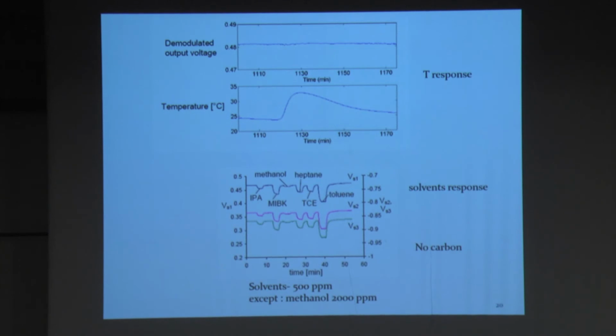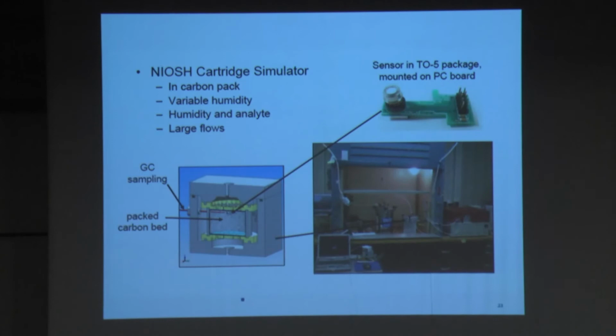Okay, here's the demonstration of the temperature dependence of the system. We increase the temperature, but the signal remains flat. And on the bottom part, you can see some signals after exposure to different solvents. Okay, so all three bridges act very nicely. So what we did next, we packaged it in a TO5 with a filter, inserted it in a carbon bed, and tried to see how they perform.